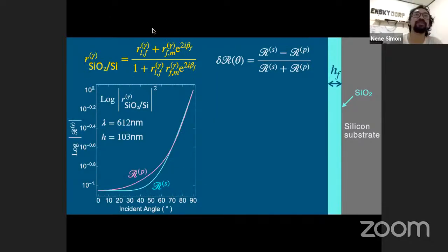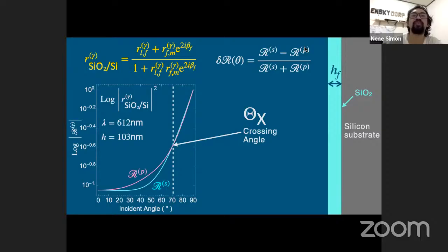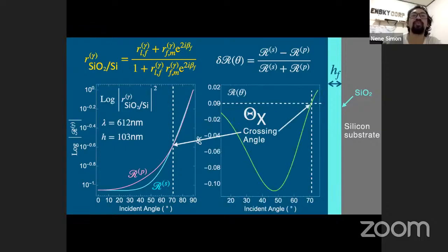So here is our equation for the reflection coefficient. To calculate the reflectivity, we get the modulus square. And I'm showing in this plot the reflectivity in logarithmic scale. I want you to notice that for an oxide thickness of 103 nanometers at an incident wavelength of 612 nanometers, the two curves intersect each other. And that intersection is the crossing angle. That's where the S and P reflectivities are equal. It can be more appreciated when we plot the degree of polarization itself, and the crossing angle is at the intersection of the curve with the horizontal axis.